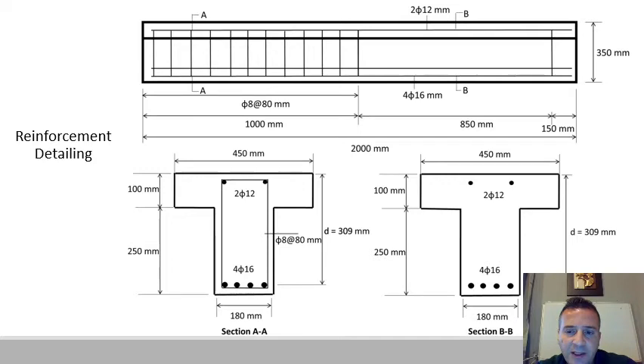Since we want to investigate the shear performance, the loading will be 1-point loading, 3-point bending, where the loading will be applied here. One side of the specimen was heavily reinforced with stirrups so that this side won't fail during testing. And this side was left without stirrups, shear deficient. So basically we can find the contribution, how much V sub C plus V sub F will be.